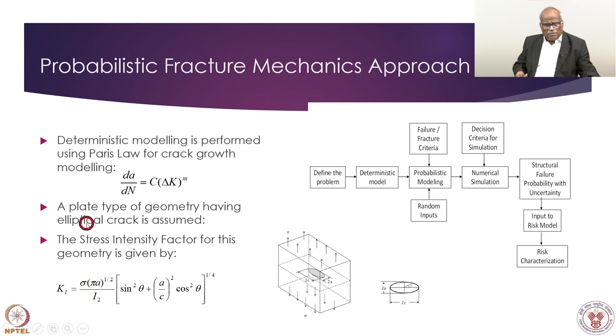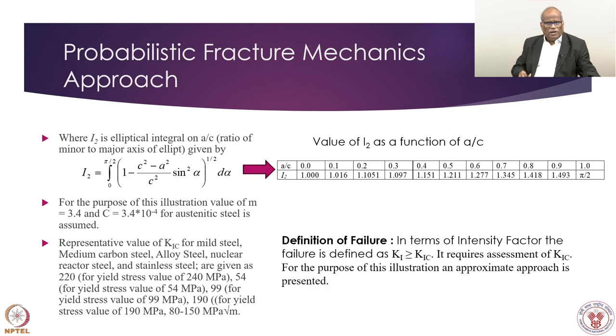So what it means is that if I have the stress intensity and if I have I2 defined, because I2 becomes part of the stress intensity. If I define I2, that is the elliptical integral on a to c ratio, that is the aspect ratio, the ratio of minor to major axis, given by I2, then we can create a systematic table for various aspect ratios, showing what the I2 will be. And this is readily available here. So having done this,